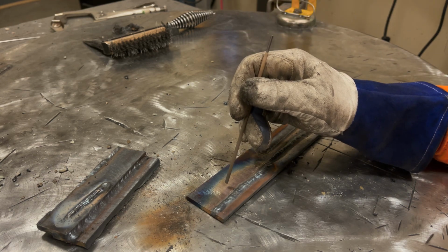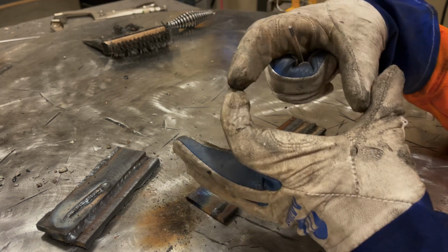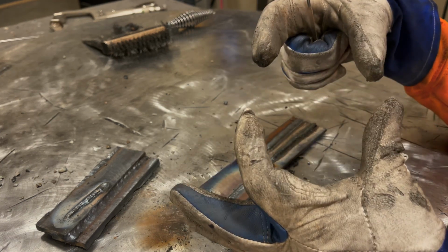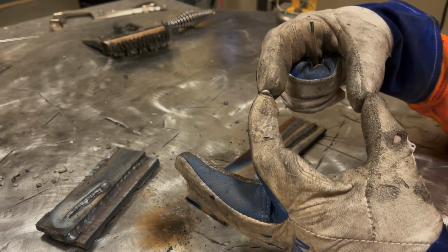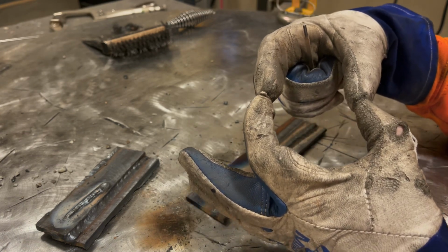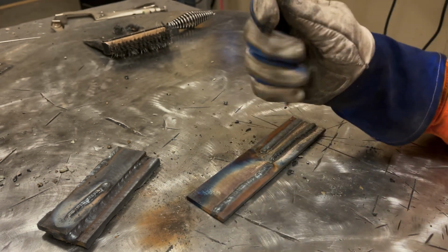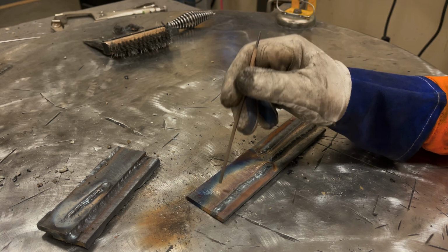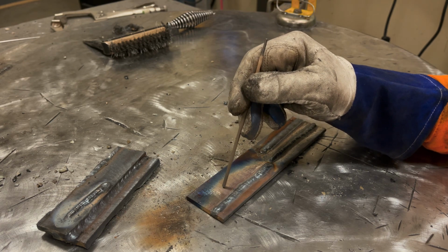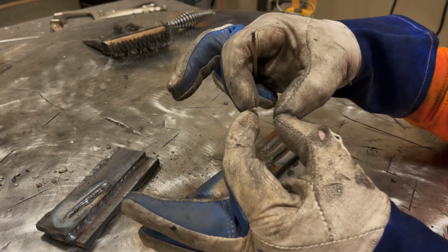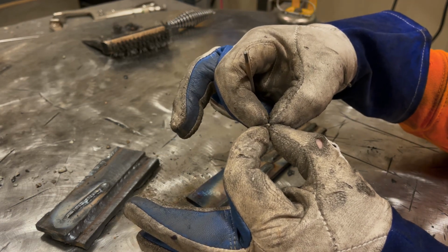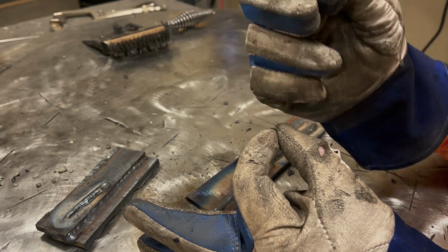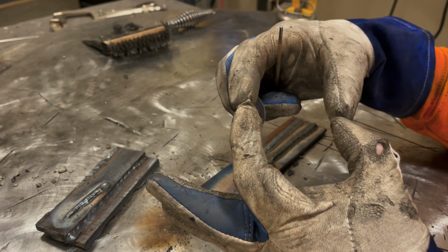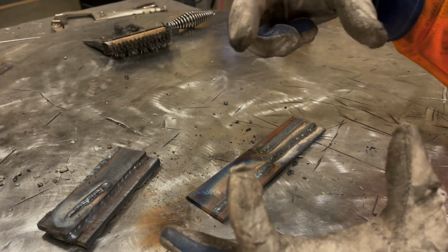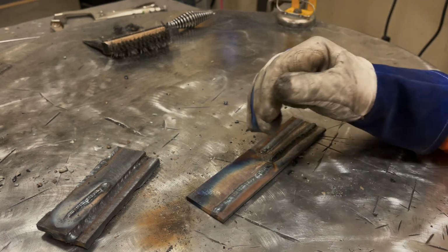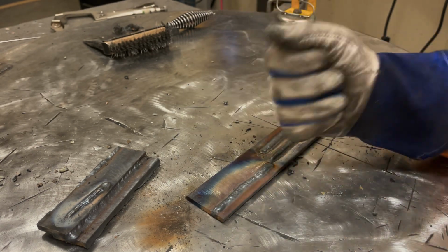When you drag that puddle and it maintains its shape, so it's eye shape or it's oval shape, and you just keep that shape where it's not lengthening like this and it's not disappearing, that's telling you that all your conditions are good, that your travel speed is good, that your amperage is good, that your arc gap is good. You just slowly drag that molten puddle. Anytime that puddle turns into like an egg shape, or a figure eight or a peanut shape, where it goes from this to this, you're traveling too fast. If it starts going from like this to like this, or like super long, you're traveling too slow, or your amperage is too high. Not really too complex, but you'll get a feel for it.